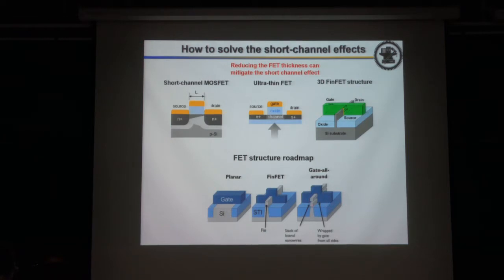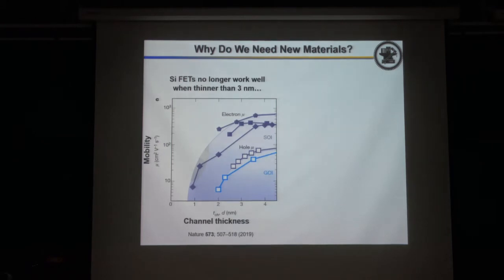And now, if we want to push further into 5 nanometer or even 3 nanometer technology, they now try to use the so-called gate-all-around structure like this. So this is the channel, and the gate is surrounding the material. So you have to reduce the material size at the same time. But what's the problem if you further thin the materials? This is the problem, because this is mobility, and this is channel thickness. If you want to further reduce the gate length, then you have to thin down the thickness. So you can see the electron or hole mobility becomes smaller and smaller, and eventually it doesn't work.